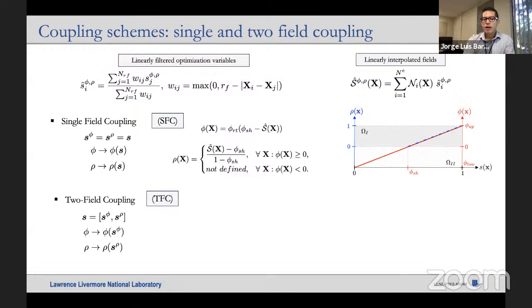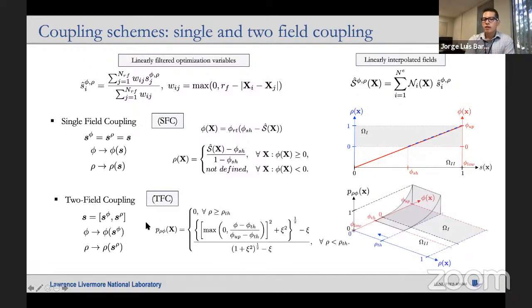But of course, since here you have completely independent density and level set fields, the way we couple them is a little bit more intricate. And the way we did this is by introducing a penalty term. What this expression says is that anywhere, again, this is material omega one or material omega two, where you have a small density, so anywhere below this rho threshold, we penalize positive values of the level set field. So if the density is low, we will make the level set field go below zero such that a hole is nucleated in your problem, right?